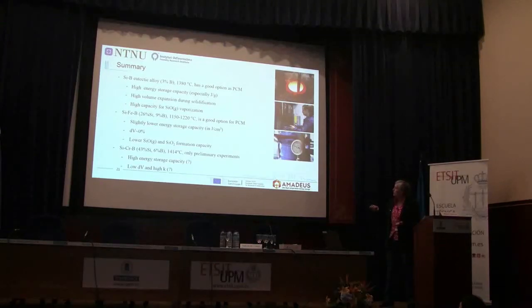Maybe our favorite for now is the iron-silicon-boron alloy, which has a lower eutectic temperature; it will solidify around 1200. This is what we measure. So it's a good option for the phase change material. It has a slightly lower energy storage capacity, however not very much, still quite good. The volume change is around 0, so that is a good thing, and it also has a quite low SiO and SiO2 formation capacity. So it has been a very good thing so far.